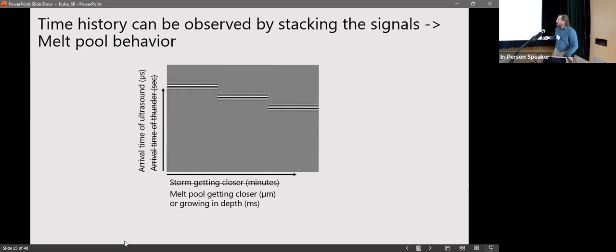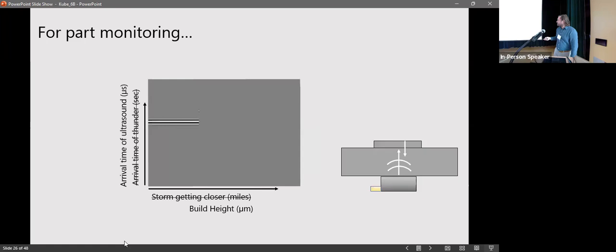For the melt pool side, the vertical axis here is the arrival time of ultrasound. As the melt pool gets closer to your sensor, it decreases. So you see a decrease in the arrival time, and that corresponds with the melt pool getting closer. For the part monitoring, we get reflections from the topmost layer of the part. So this might look like the very first signal that we collect, and then we add a layer, we get another signal, and so forth.